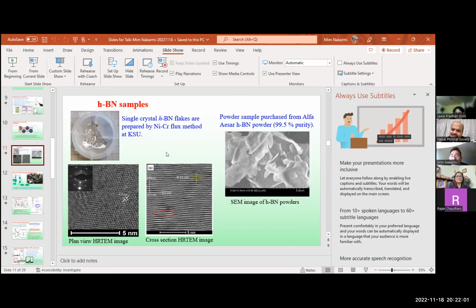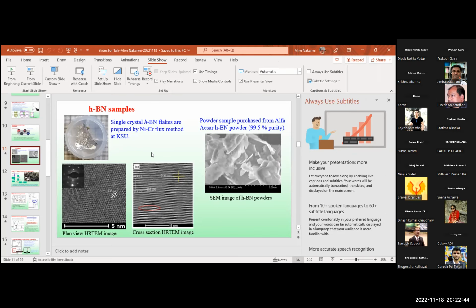I don't know that much, because I never just heard about it. I bought and got the sample from them. But a little bit is, they use nickel, chromium, and then put some boron nitride in the crucible, and it is heated to a very high temperature, like 1500, 2000 degrees, and then after that it's cooled down slowly, and then some of the material sticks to the plate on the crucible.